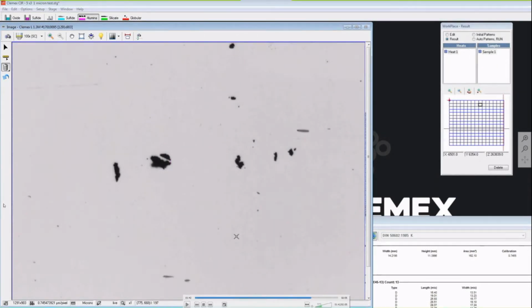You're going to notice that this was detected because of its rough shape. As I told you, alumina has a characteristic to be a rough shaped inclusion, but the operator knows that this is not an alumina inclusion. This is actually bad preparation.